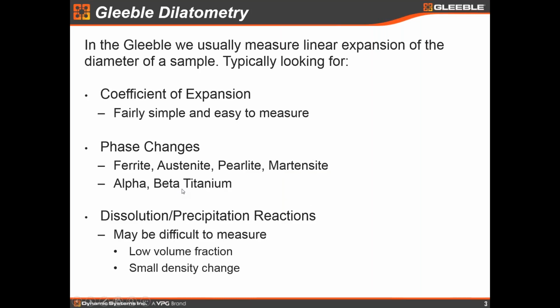Alpha and beta titanium are also very critical. There are a lot of titanium alloys that are designed around the alpha-beta titanium transition. The alpha-beta titanium transition is a much lower volume change transition than the ferrite-austenite transition in steel, so it's a little more difficult to measure, but it still can be measured in dilatometry.